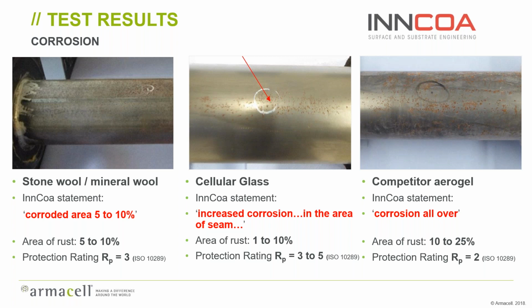Cellular glass, often chosen to try to mitigate against corrosion under insulation. Incoa said that there was increased corrosion in the area of the seam and that the area of rust was 1 to 10%. And they gave it a protection rating of 3 to 5, again against that ISO standard. So still at the low end of that protection range.